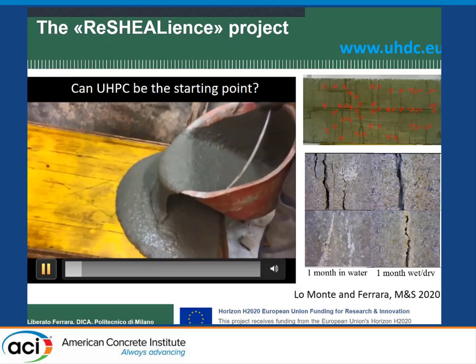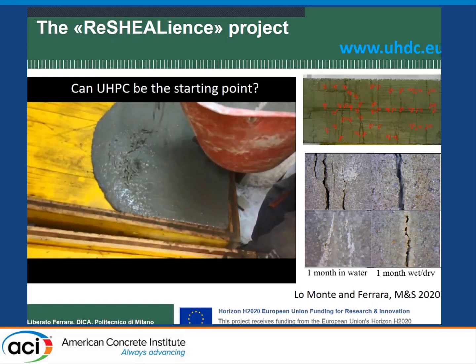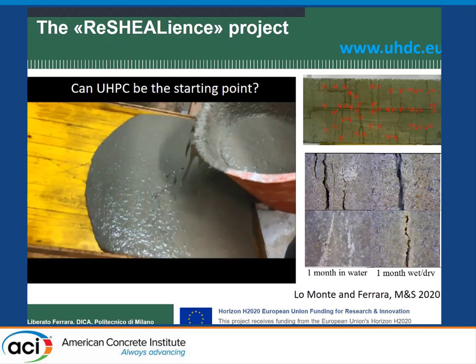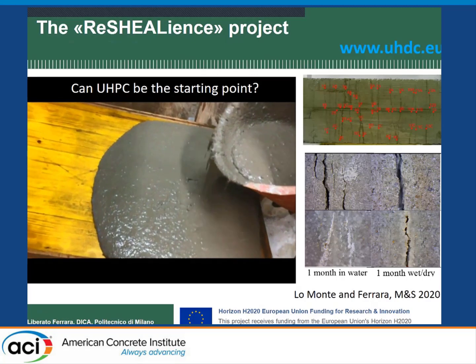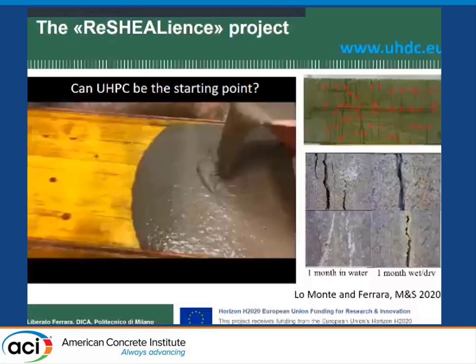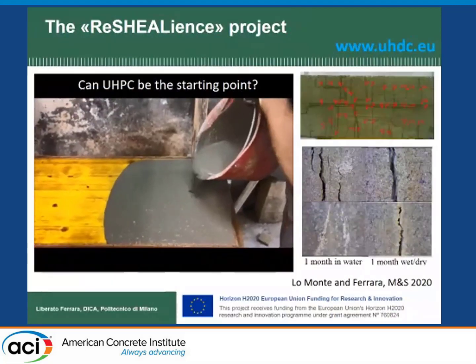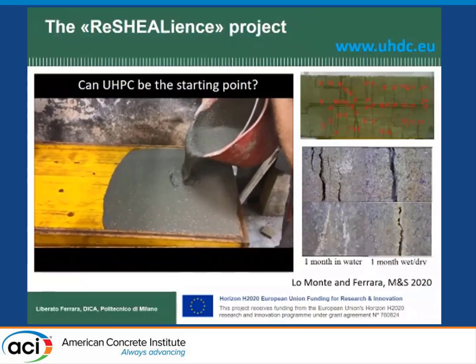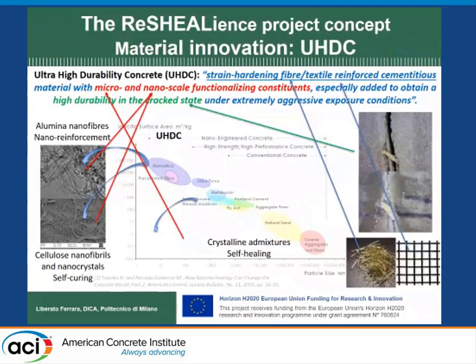We started from our long-time lab experience on UHPC, dealing with the capacity to induce multiple micro-cracking and also investigating self-healing, and said, okay, let this be the starting point and let us see how we can engineer the material in order to have enhanced durability, targeted to the conditions that we have to meet in this application. So we have been working with dispersed steel fiber reinforcement, but also with micro and nano functionalizing constituents: nanocrystals and nanofibrils of cellulose for self-curing, alumina nanofibers as nano reinforcement, and crystalline admixtures for self-healing.